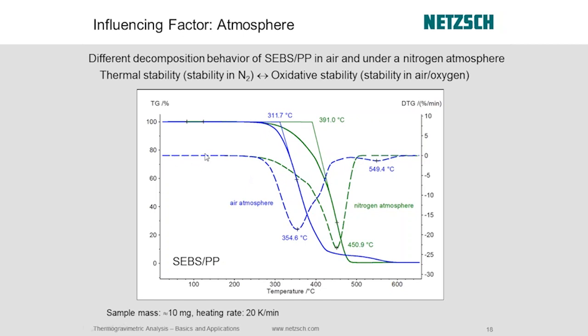But in air, we can definitely see, especially if you look at the derivative, this totally different profile in an air atmosphere. We definitely have two real steps going on here, and maybe even something else here as well. So in an air atmosphere, you get completely different characteristics. The onset of breakdown is significantly different, and the maximum points where it loses most of its mass have changed by almost 100 degrees as well. So there's a big difference between running thermal stability measurements in nitrogen versus oxidative stability measurements in air. I think we covered this. You can see your peak temperatures have shifted by about 100 degrees in that maximum mass loss.